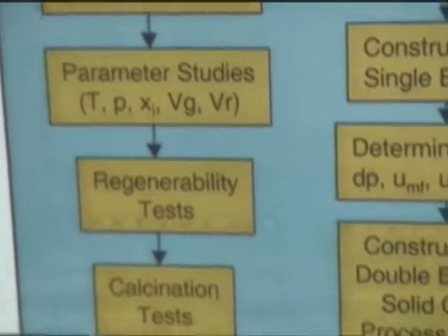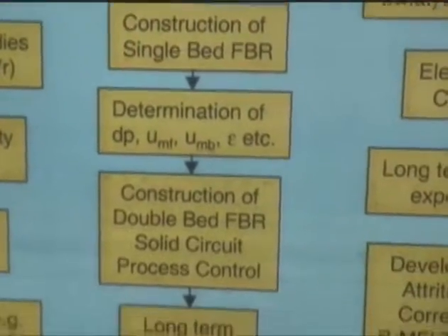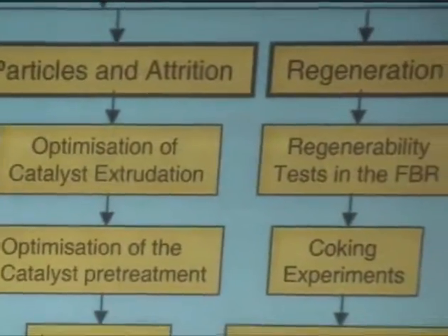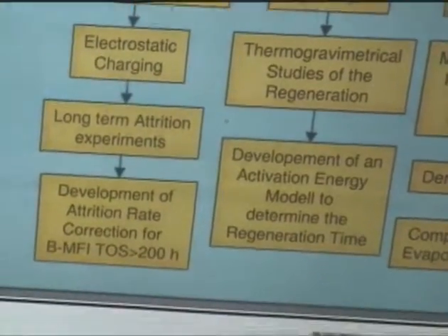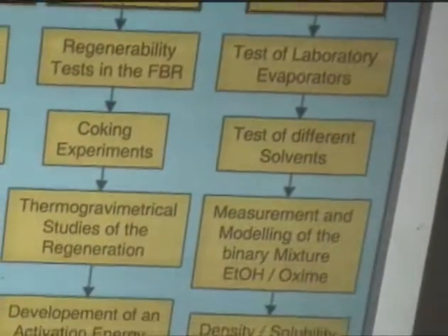We have done quite an extensive screening of different catalysts, and we studied that mainly in a fixed bed reactor, but then we realized that we needed a fluidized bed reactor, so we built up a single bed fluidized bed and also a fluidized bed with continuous regeneration. That means a system similar to an FCC unit. Then we studied particle size and attrition, we studied regeneration, and we studied also the evaporation of the oxime.